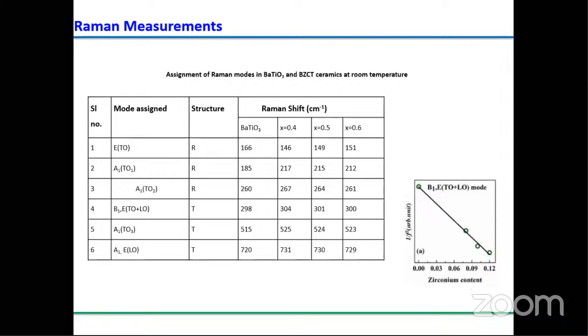So here is one beautiful result that we found. Now I try to draw 1 by f square. f is equal to square root of k by m, so f square is equal to k by m. That's why we have written 1 by f square is proportional to effective mass. When you observe here, as the zirconium content is increasing, 1 by f square is decreasing. That frequency is shifted towards the lower side. We have observed 304, 301, 300 as the composition increases from 0.4 to 0.6, and they exhibited linear behavior. What does that tell us? Again, it tells us that whatever atoms we are trying to dope, they entered into the lattice positions. That's why we got the linear behavior of 1 by f square.